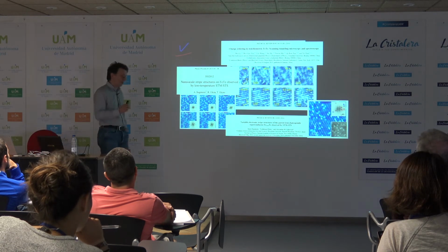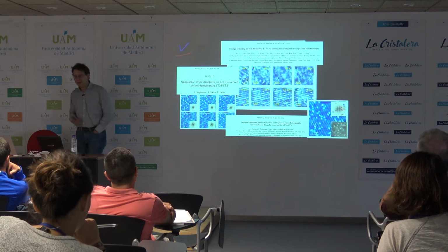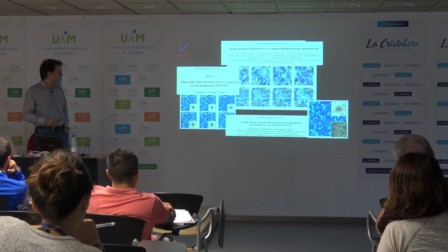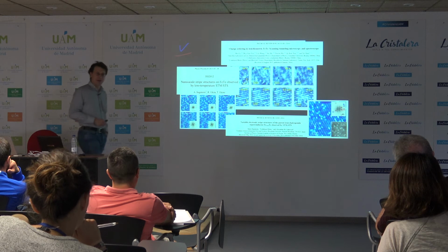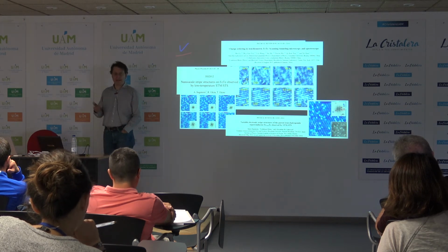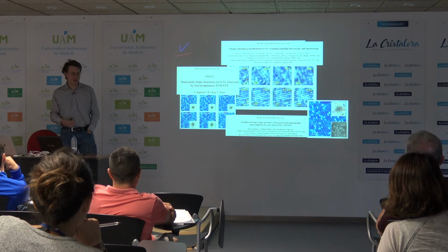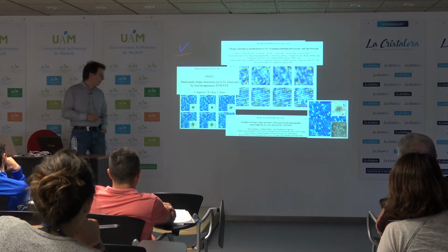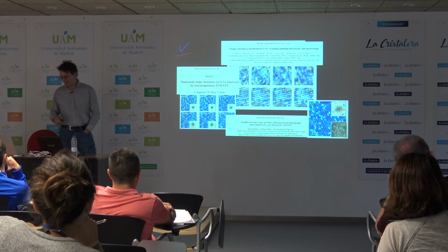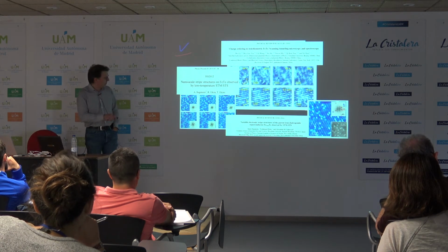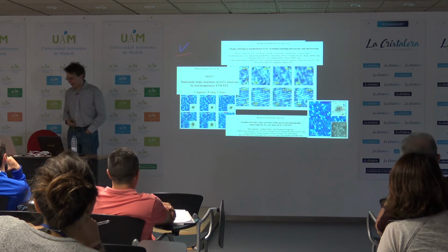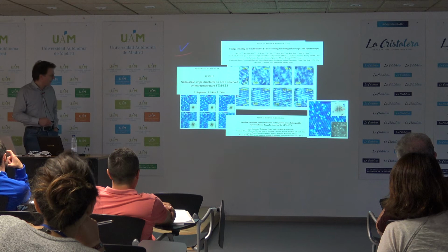But the missing piece of the puzzle was to understand that the fact that one sees the stripe order simply meant that the tip had become magnetic in the course of the measurement, because one picks up these iron atoms almost accidentally, even if it's not on purpose, by preparing the sharp tip. So effectively, all these studies have been spin-polarized STM studies without noticing.